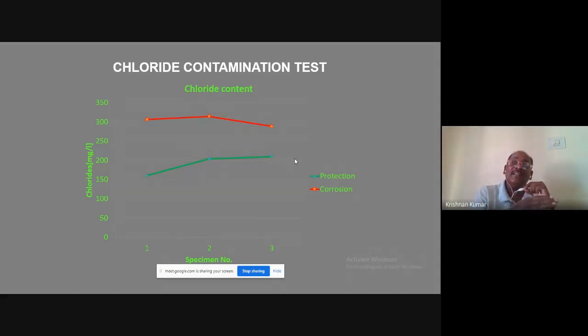So automatically, near the steel reinforcement, whatever chloride is there will migrate to the surface level. That is coming into dissolution in that lime solution. So then finally that lime solution can be removed. After the electrochemical removal process, you can dry the surface and do the complete surface painting, all these things, for further nice protection of your structure.